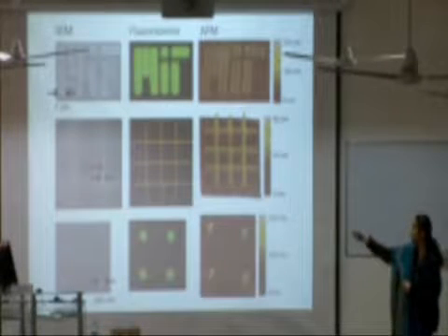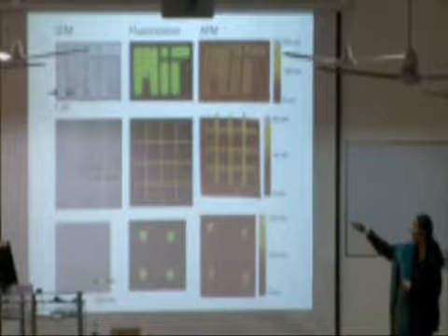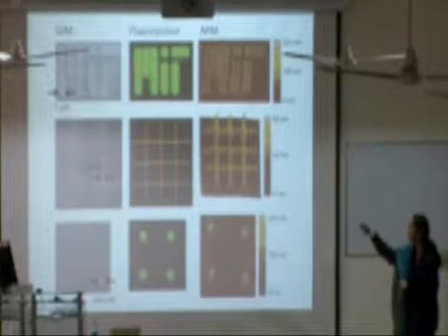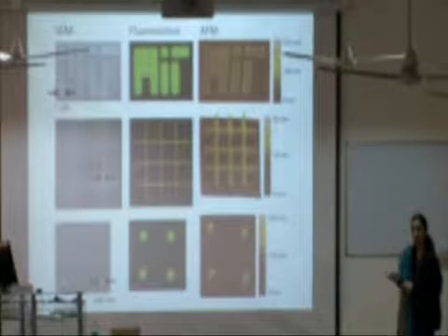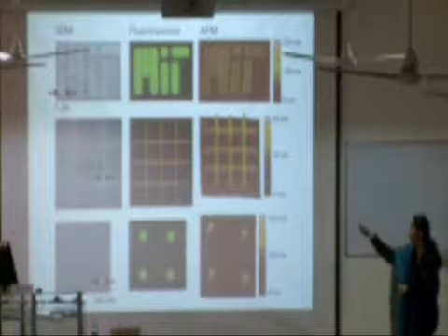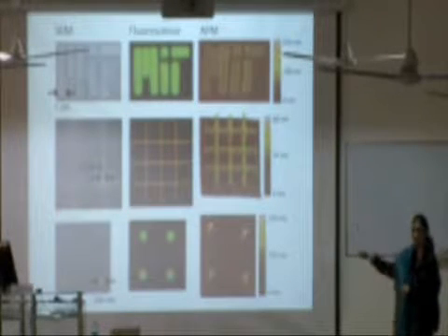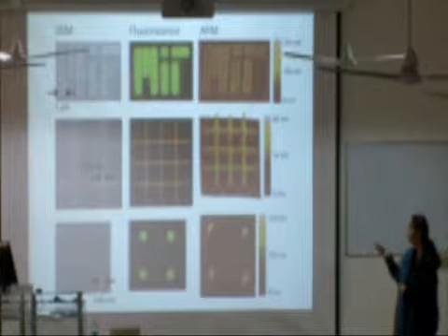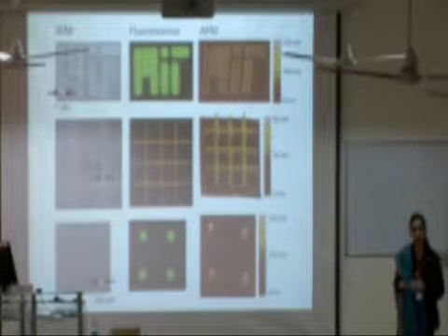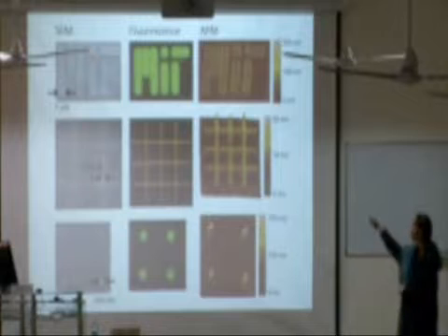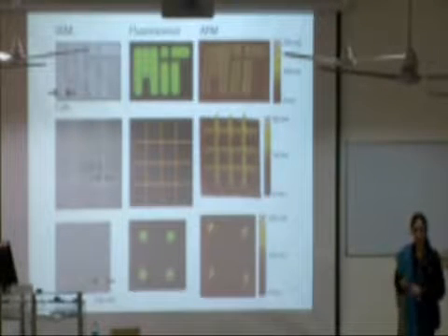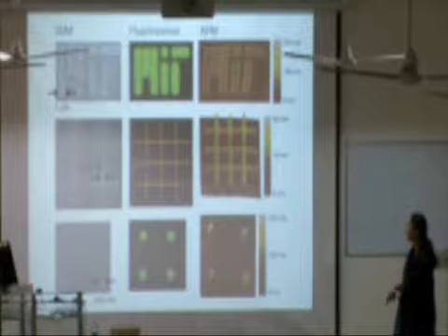As you can see from the SEM image, the length scale is a micron. We have really nice ordered films. There are no visible cracks. And cadmium selenide quantum dots, since their band gap lies in the optical region, they fluoresce, and the fluorescence looks really nice. And these are two different size quantum dots, which shows that we can get different colors. If you look at the atomic force microscopy, which gives you the height profile of the films that we've formed, you see that they're very nicely structured, and there is no measurable surface roughness to the films that we've formed.